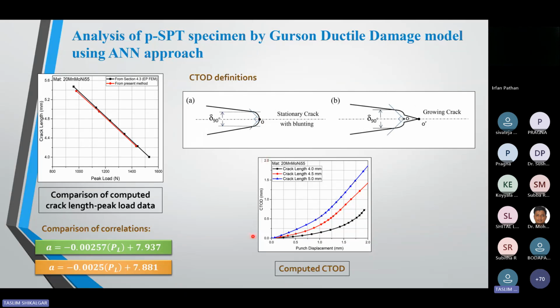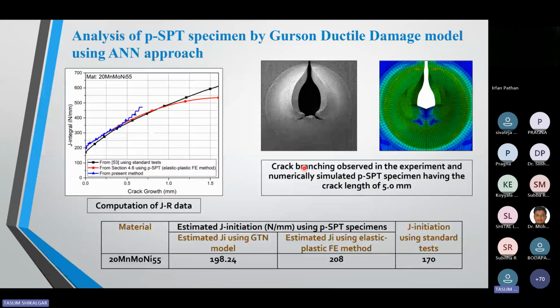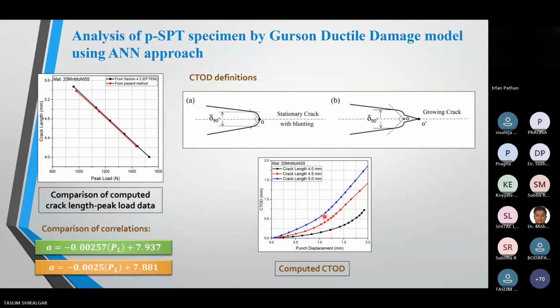I generated CTOD versus punch displacement. I calculated for different crack lengths, and as my crack is increasing, my CTOD is increasing. I observed this from this type of graph. So the next task is how we can calculate CTOD versus crack growth data.